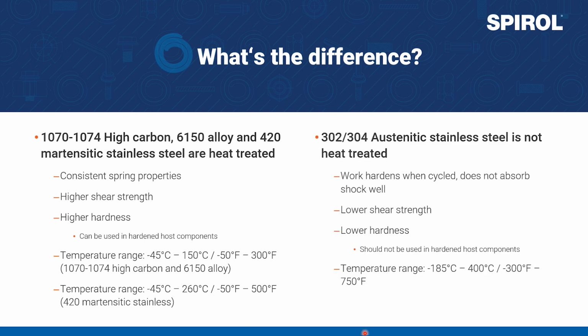Austenitic stainless steel cannot be heat treated, and it work hardens as it's cycled. As a result, this material does not absorb shock well, and it's not recommended for use in applications where dynamic loading is present. Austenitic or 300 series stainless steel has lower shear strength and hardness as compared to the carbon and alloy steel, as well as the 420 chrome. In addition, this material is generally not suitable for use in hardened components.